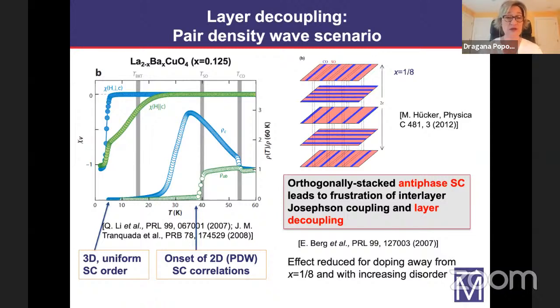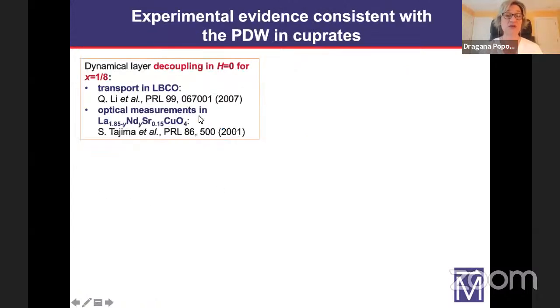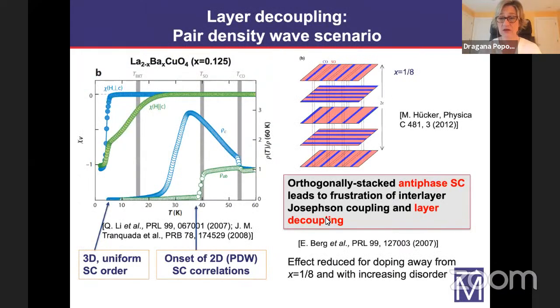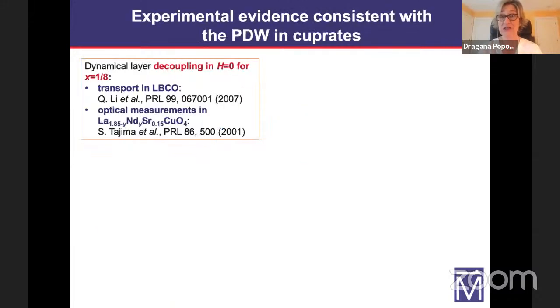In addition to this work by John Tranquada and his group, there was another, earlier paper, in which they used a material from the same family and changed the doping, and they found again that as the material was tuned into this regime with stripes, the interlayer Josephson coupling was reduced. For samples that were away from 1/8 doping, and I mention this because this effect is supposed to be most pronounced at 1/8 doping, and it should be less pronounced also with increasing disorder.